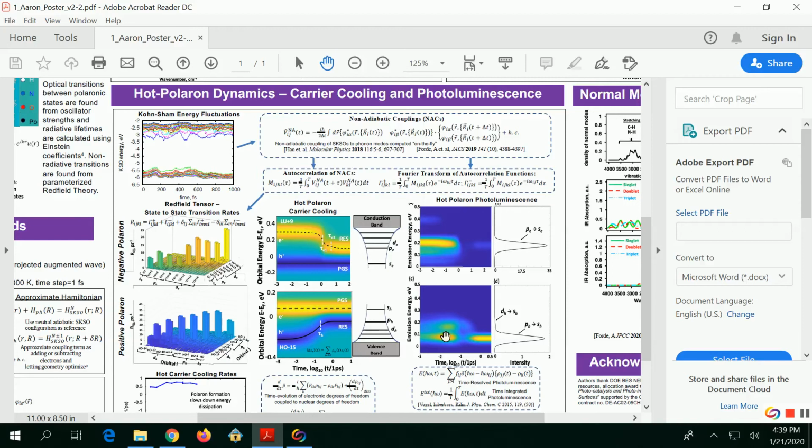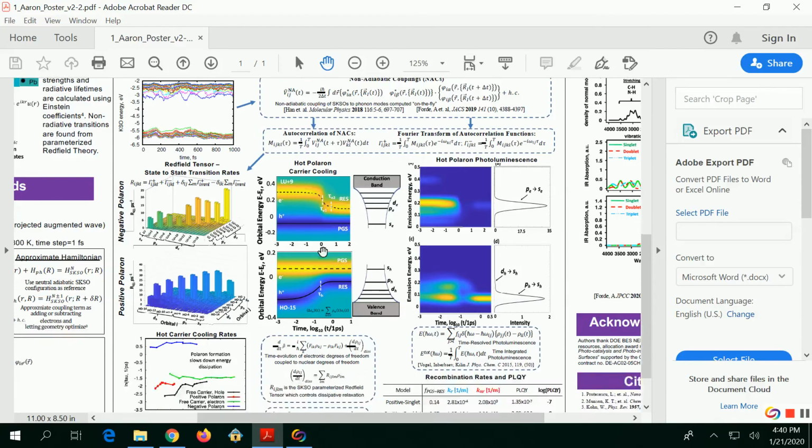In this case, we see an interesting contrast in their dynamics. The positive polarons show a pretty single exponential decay, with no kinks as it's relaxing, whereas for the negative polaron you see something that looks similar to a bi-exponential decay, where there's a mismatch between relaxation rates. I'll characterize more on that in a little bit, or actually it might be a good time to go there now.